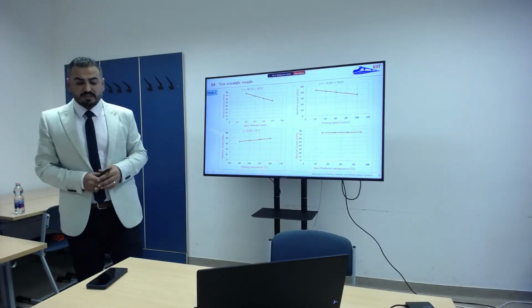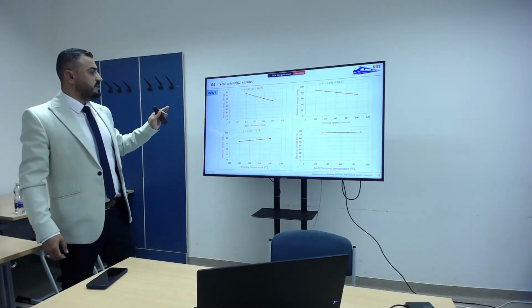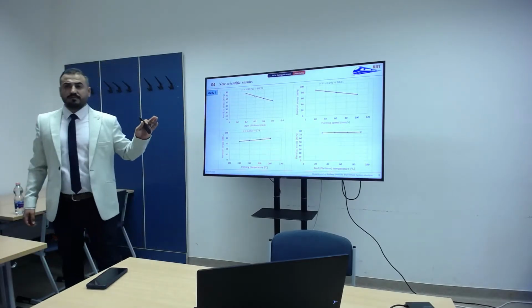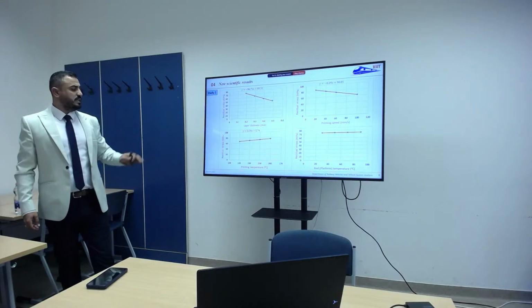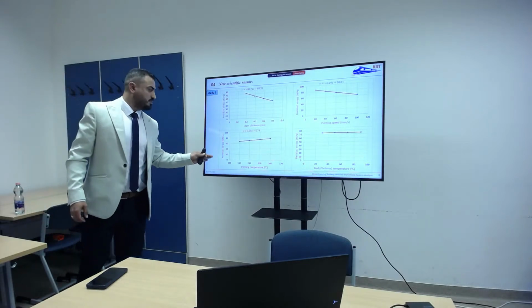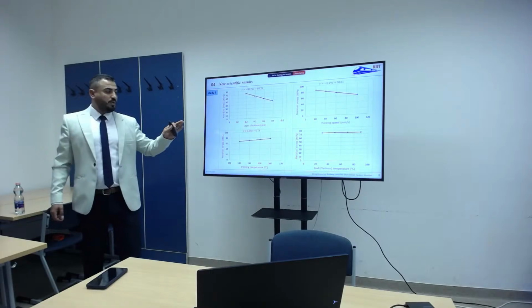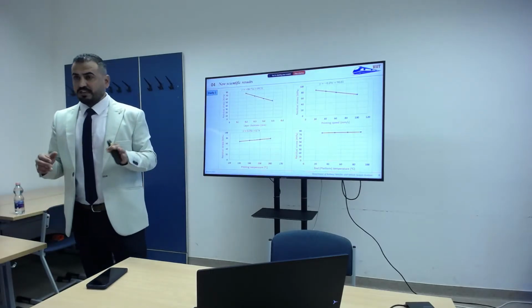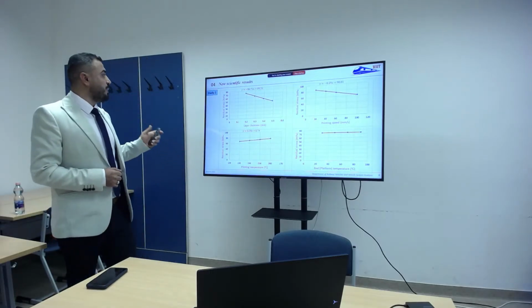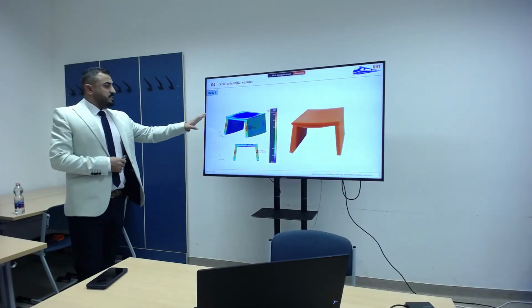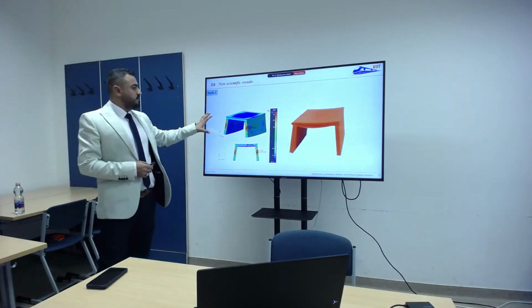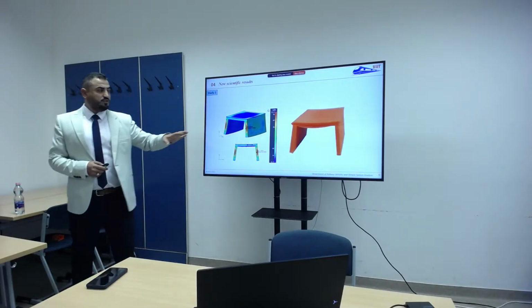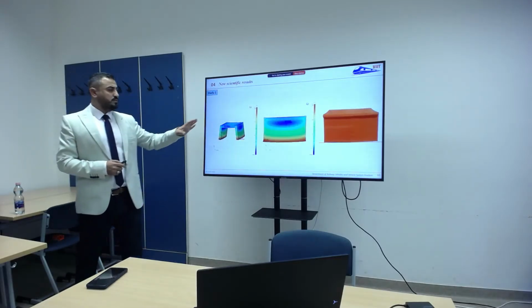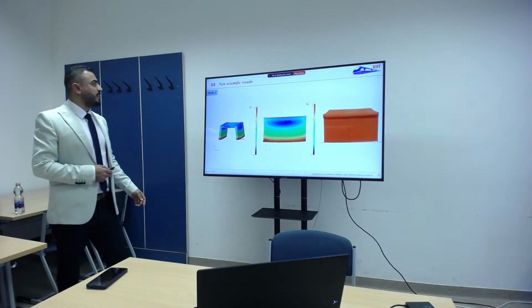For the manufacturing parameters, I found that the layer thickness and printing speed negatively correlated with the value of residual stress, and the printing temperature was slightly positively correlated, while the bed platform temperature does not have any impact. And here you can see the visualization of the software simulation and the actual printed part, and this is the side view to see the warping deformation.